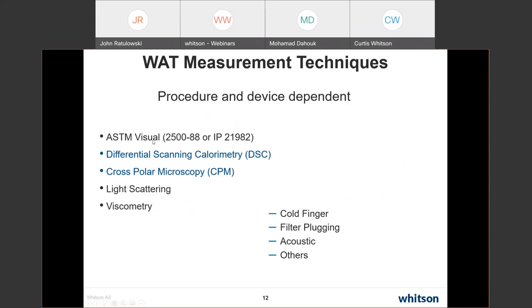The two most popular methods are DSC, differential scanning calorimetry. This looks at the heat signature of the actual crystallization. There's a heat of fusion associated with that. And so with DSC, we're looking for a signature that shows that wax is actually crystallizing. Remember that the crystalline waxes, the normal paraffins, have a high heat of fusion, so they're going to be easier to see on a DSC. The microcrystalline waxes have a much lower heat of fusion, and so it may make it a little bit more difficult to pick up something like that on a DSC.